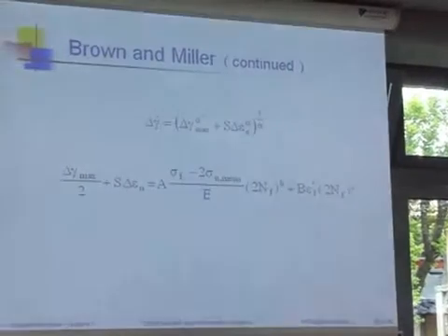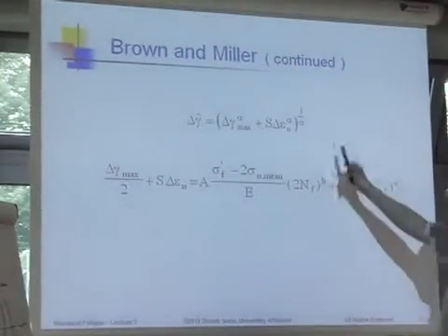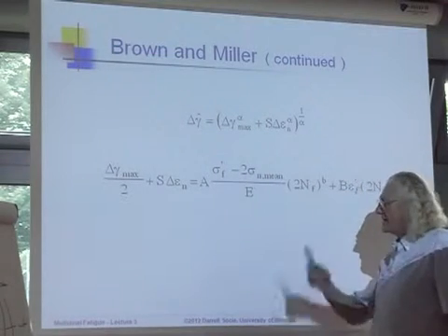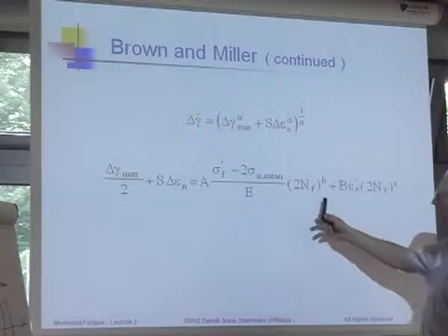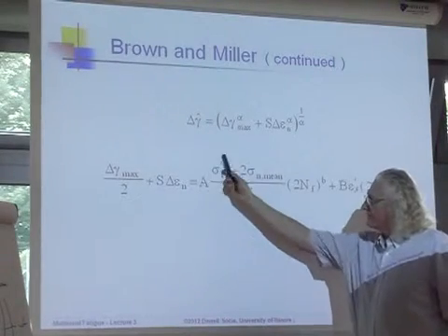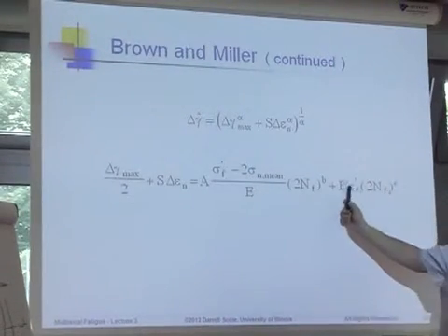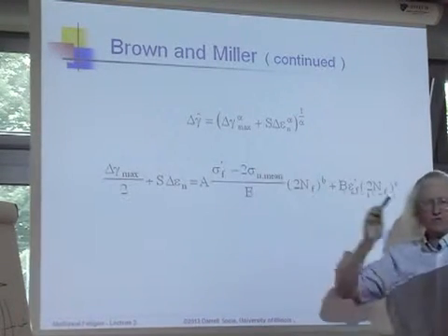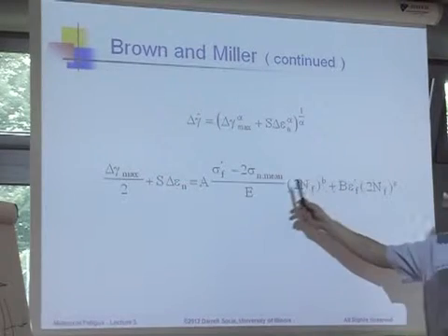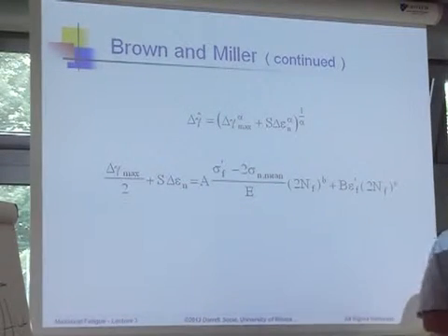And then to make it look like all other fatigue data, that's what their formula is, they write it to look just like strain life data, and so you have a few extra constants. You will recognize these are the traditional strain life constants here, epsilon f prime, and then slopes b and c, and so forth. These constants A and B are not adjustable constants.